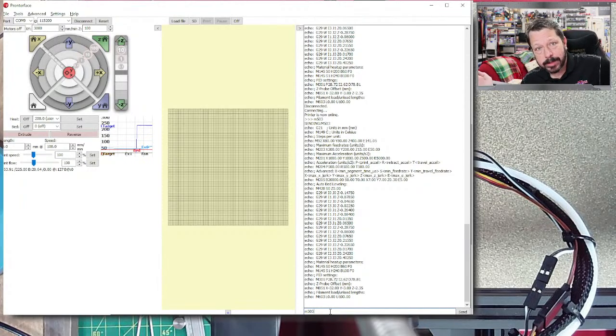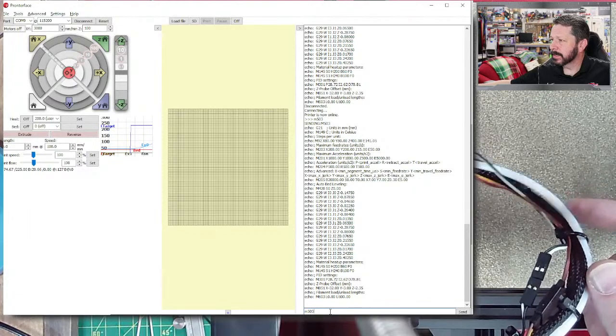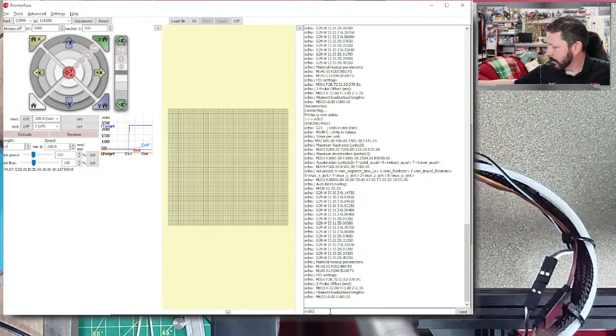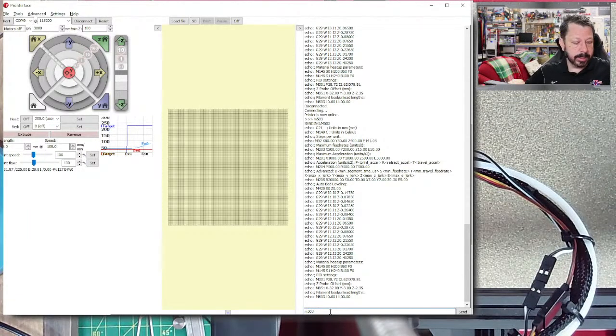the hotter you go, you get to the point where this tube right here, this guy that's holding the filament, it goes down into the hot end, and it is made of a Teflon material, and Teflon begins to break down in that range, 240, 245, somewhere in that range that PETG prints at. So you typically have to print at the lowest temperature possible for PETG.